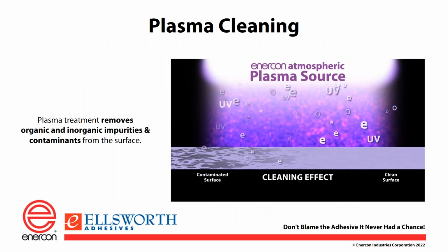So what does plasma actually do to the surface? Three things. It cleans the surface. Now, the one that's not mentioned here is that once you treat something, it takes the static off the surface. So anything like dust or anything being held on by static will go away. It kind of gets blown off just by the pressure of the air. But it also can remove organic and a few inorganic materials. You see there on the left, material comes in dirty and goes through the plasma, and the plasma will clean those organics off. Now, some of the inorganics are a little bit harder to clean, so it may take a pre-treatment step for those. But again, it does a good job cleaning those surfaces.